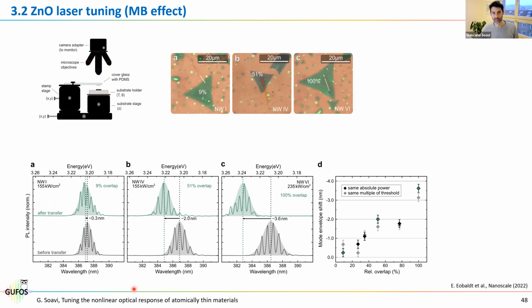And what is interesting is the following. The gray curve here is the lasing properties of the nanowires before the transfer, and the green one is the lasing after the transfer on the TMD. You see that when we have a small overlap, they look pretty much the same, although we already observe a tiny shift towards the blue of the lasing threshold. And the shift becomes very evident and very clear as we increase the overlap between the TMD and the nanowire.